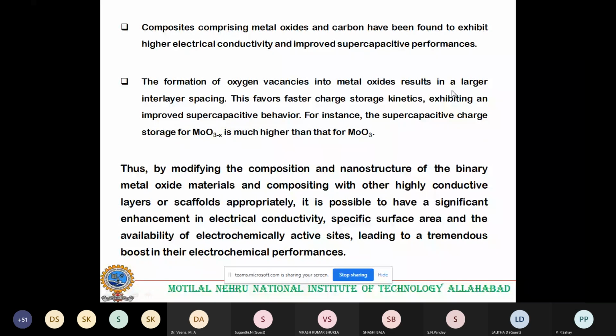So what is the conclusion? Thus, by modifying the composition and nanostructure of the binary metal oxide materials and compositing with other highly conducting layers, that is carbon and or some scaffolds appropriately, it is possible to have a significant enhancement in electrical conductivity, specific surface area, and the availability of electrochemically active sites, leading to a tremendous boost in the electrochemical performance.